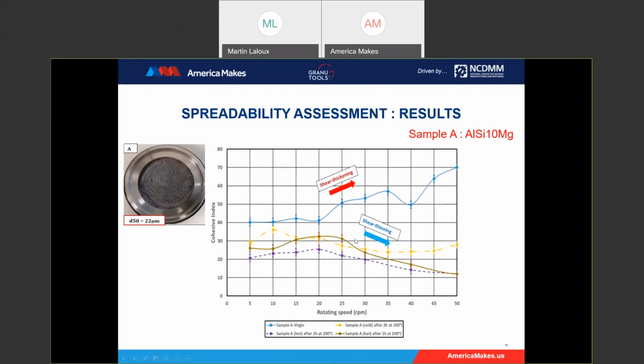When we look at the other curves, you see that the hot powder, after 2 hours at 200 degrees, has the lowest cohesive index, so it will be easier to spread, and even easier to spread at high speed. And the two powders that were heated at 200 degrees and then cooled down for 1 and 2 hours gave a higher cohesive index, but still lower than the virgin one, because the tendency to catch humidity is increased regarding sample A.